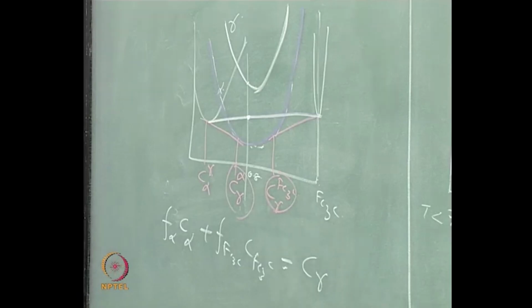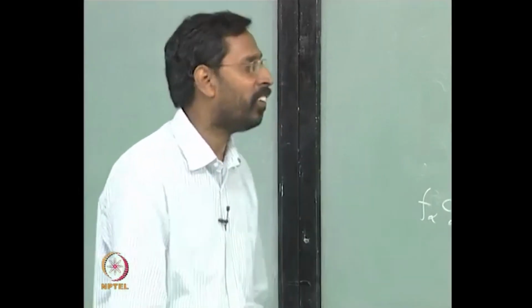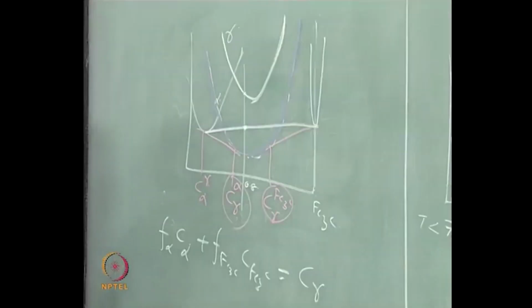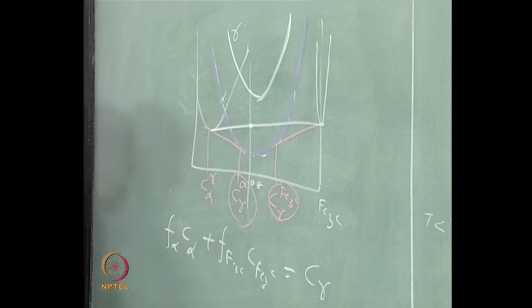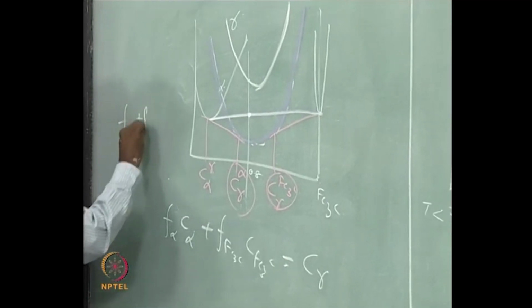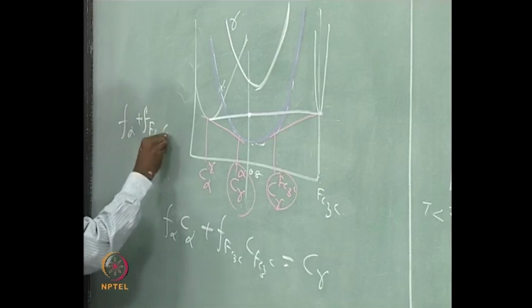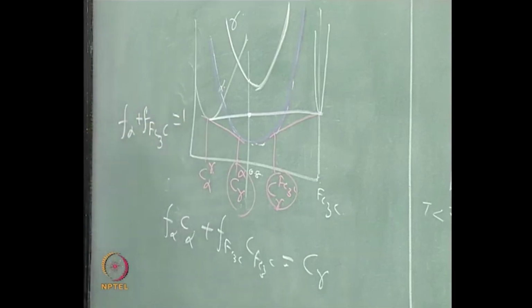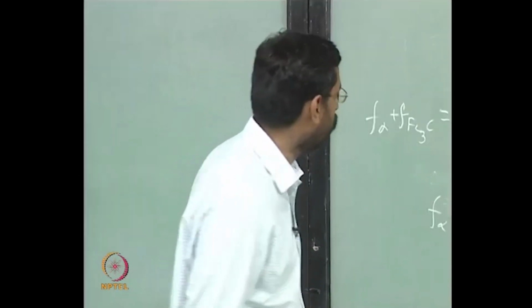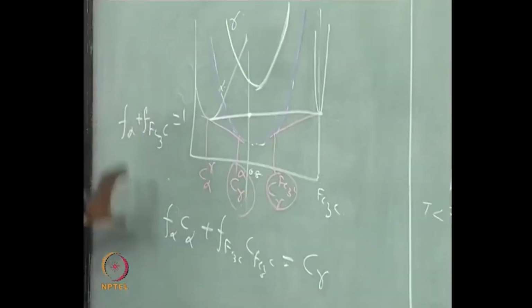But in lever rule we also use one more thing. What else we use? Just with that equation can you get lever rule? What else you need? The fractions have to be equal to 1, because after the transformation is over you know that f of alpha plus f of Fe3C should be equal to 1. That is the second boundary condition. If you do not have that boundary condition you cannot get the lever rule. So, for lever rule, these two equations are the crucial equations, okay.